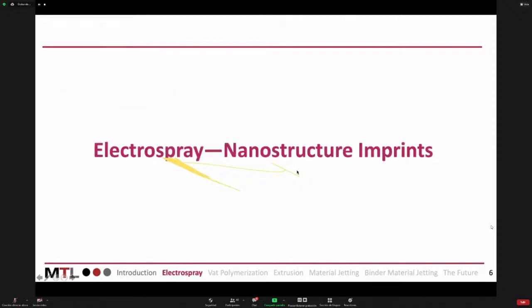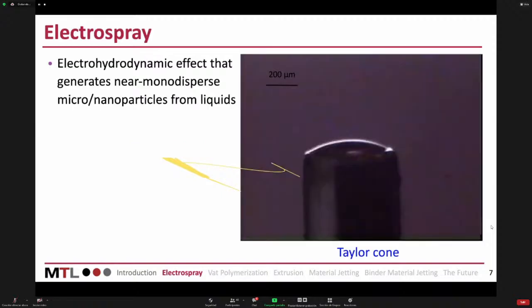So in terms of electrospray, what we are interested in is having a technology that allows you to create nanostructured imprints. It's a technology that is not commercially available, but that you can easily put together if you have a high voltage source. So if you are not familiar with electrospray, here's a video. So you see it's a capillary, and you see that the meniscus of the liquid evolves from a hemispherical surface to a cone, and then from the tip of the cone, you spray droplets.